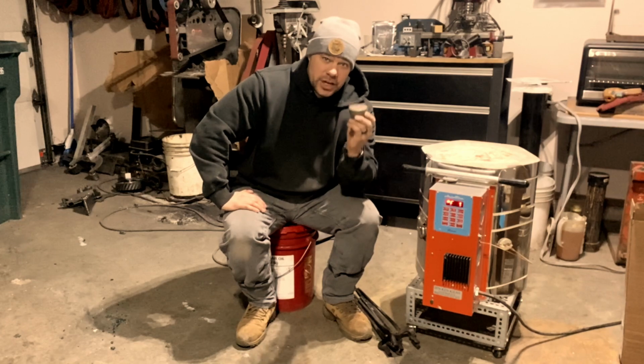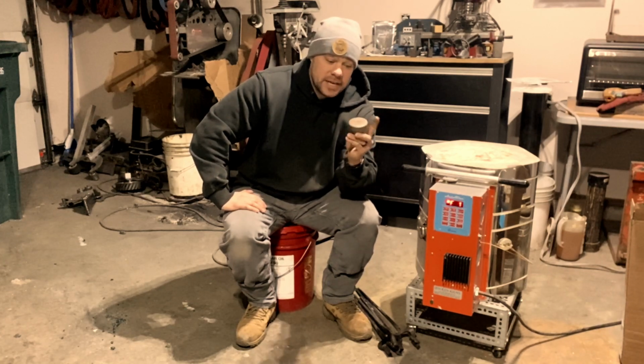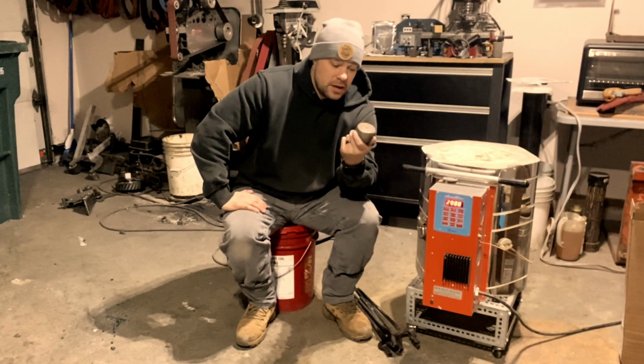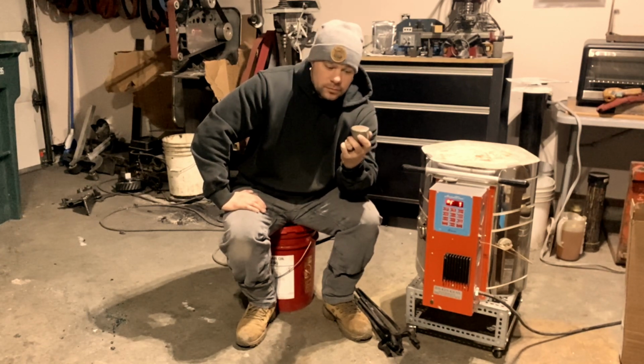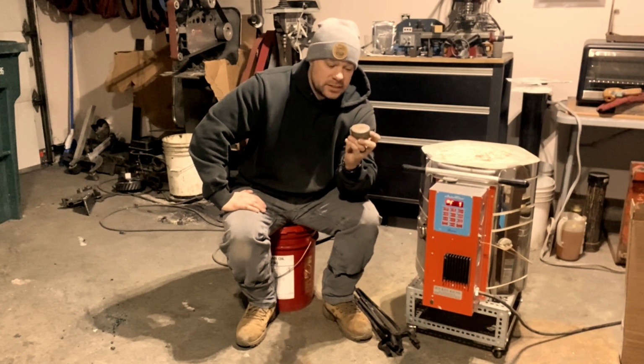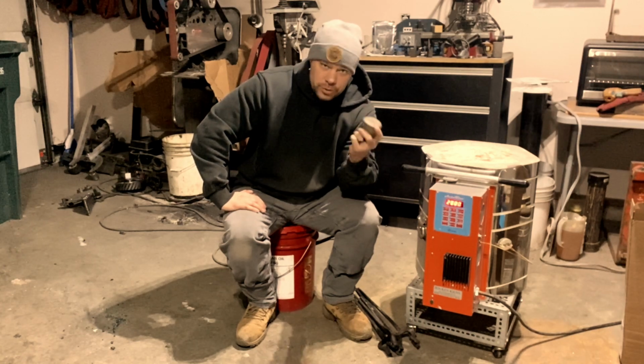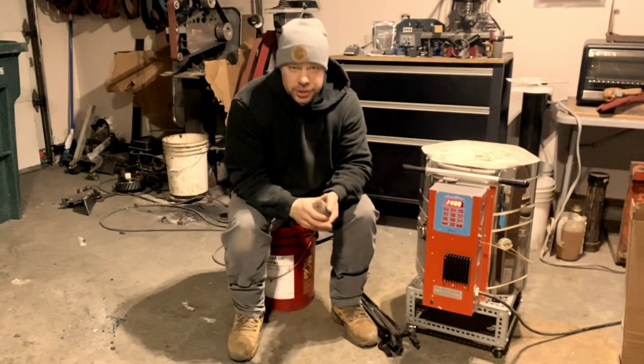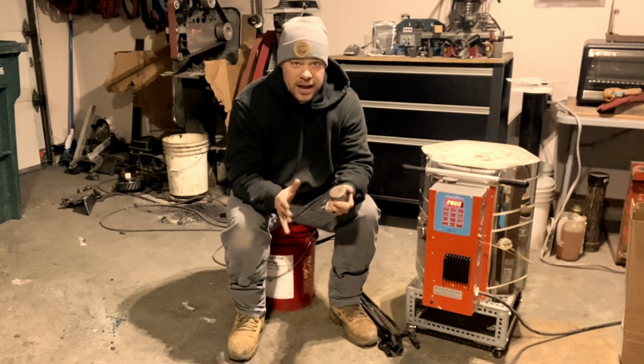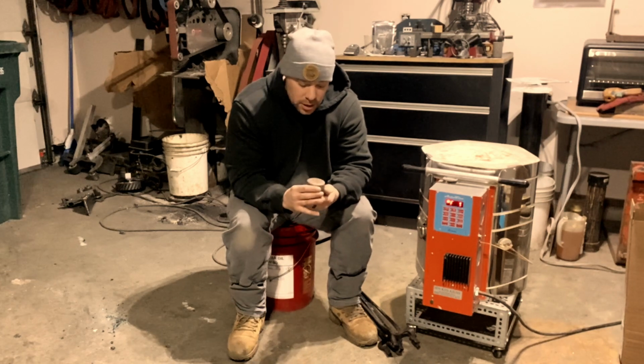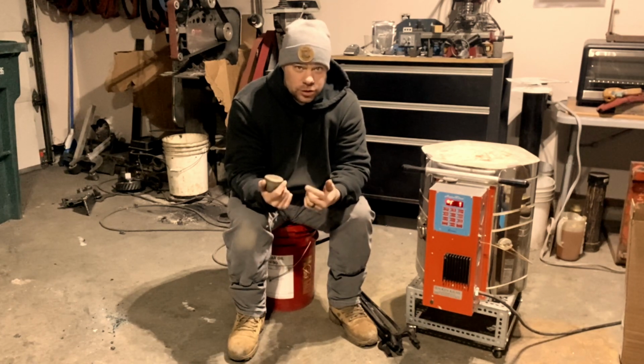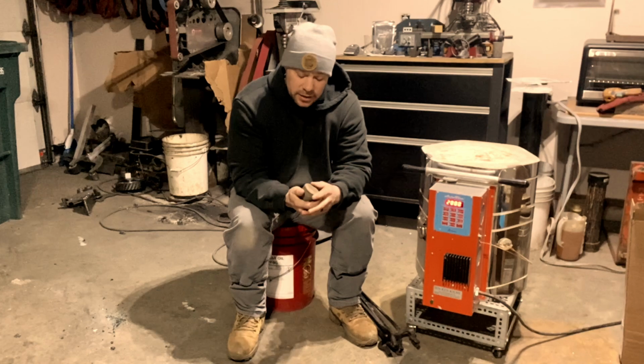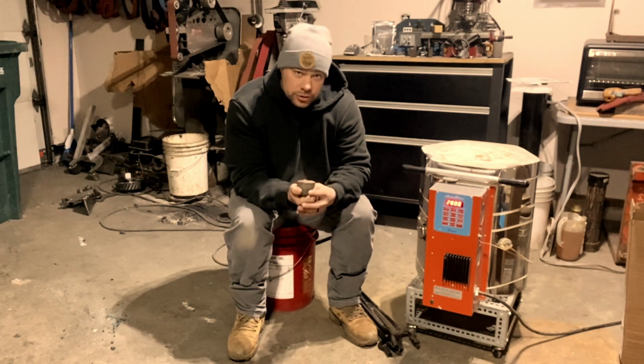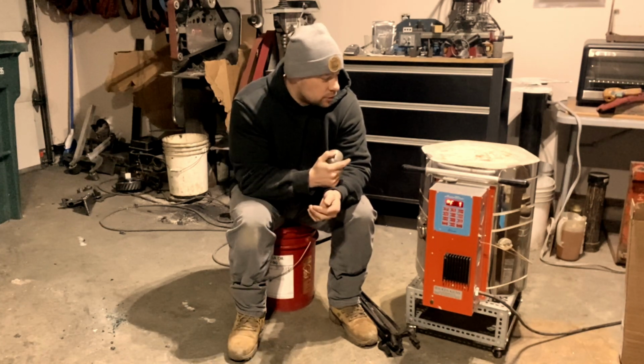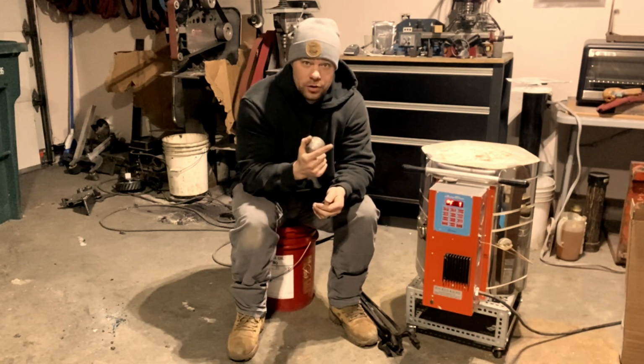And what that does is it changes the initial structure of this ingot, because as the ingot is, it's very brittle. It's crystalline. So if we were to take this right now as is and put it in the forge, bring it to temperature and start forging, the probability of failure is very high. That's why roasting is very important. You don't want to just take this out of the crucible and go forge. It's not a good idea. So 2,000 degrees for 2 hours, and then it comes directly out of the kiln and right into the forge.